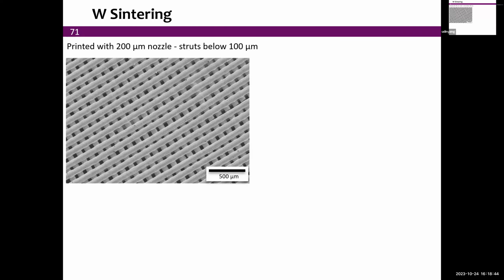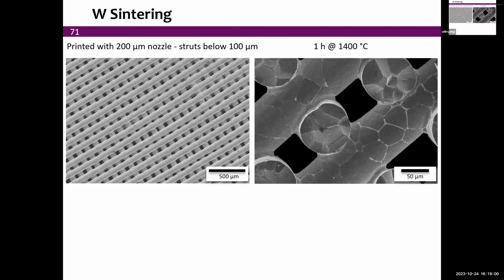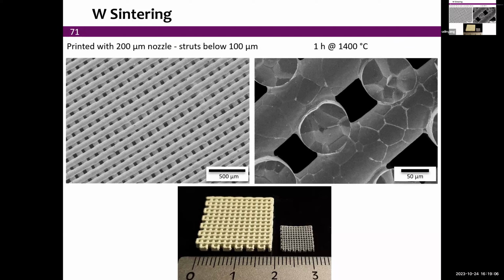So here we are. We printed 200 micron nozzles. It shrinks, and so the diameter now is below 100 micron. Probably impossible to do this with laser melting or e-beam melting without cracking terribly and all kinds of terrible surface asperities. We see very smooth surfaces here. This is 1 hour at 1400 degrees C, and of course that dramatic shrinkage that I discussed. So that's of course the Achilles heel of the